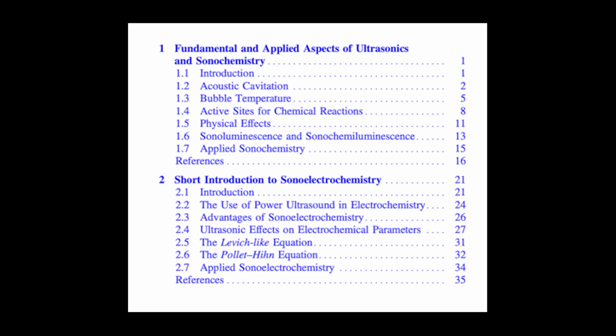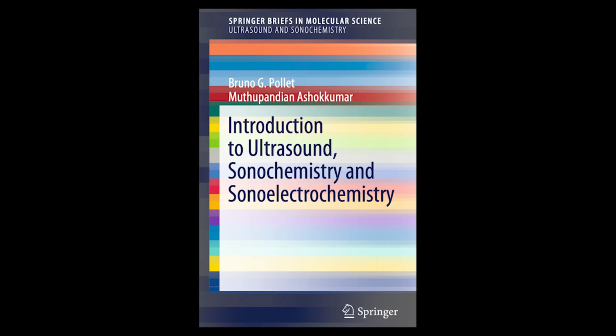But the collapsing bubbles are generating H-dot radicals, hydrogen atoms, in the core. Some of these H-dot radicals manage to diffuse out into the bulk solution. H-dot is a powerful reducing agent, it wants to give away an electron. So when an escaped H-dot radical encounters a gold ion, AuCl4 complex, in the bulk solution, it reduces the gold: AuCl4 plus 3 H-dot gives Au plus 3 H+ plus 4 Cl-.